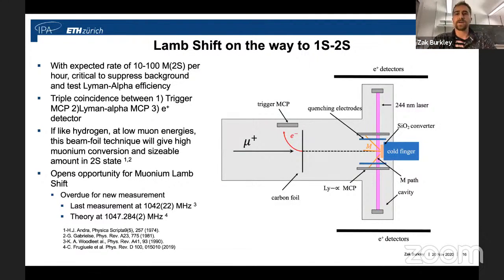So, as I talked about earlier, on the way of building our 1S, 2S technology, we realized we can also do the lamb shift measurement, because with an expected rate of 10 to 100 muonium in the 2S state per hour, it was very critical for us to suppress our background and test the Lyman alpha efficiency.